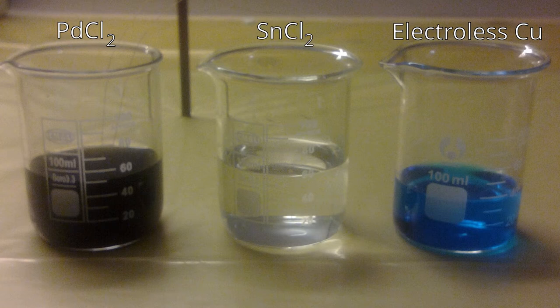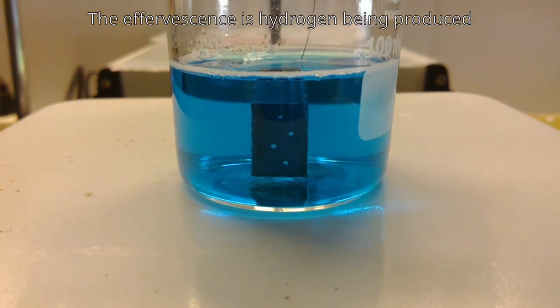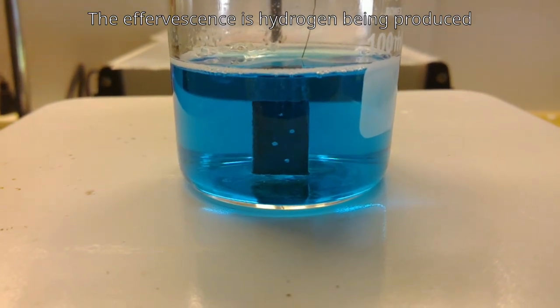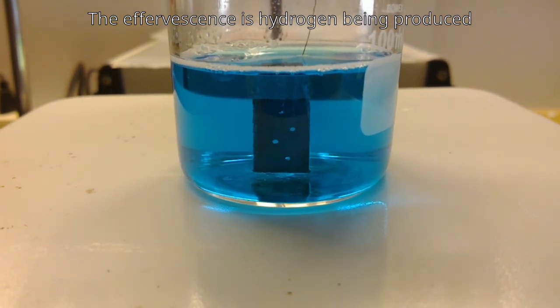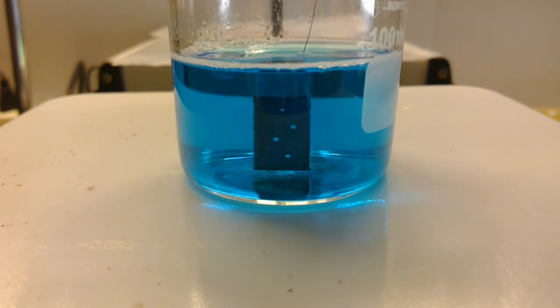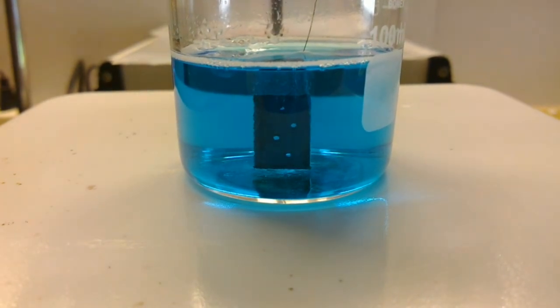After that, it is immersed in an electroless copper plating solution, which uses formaldehyde to reduce copper ions, depositing a thin layer of copper on the entire board, including the hole walls.